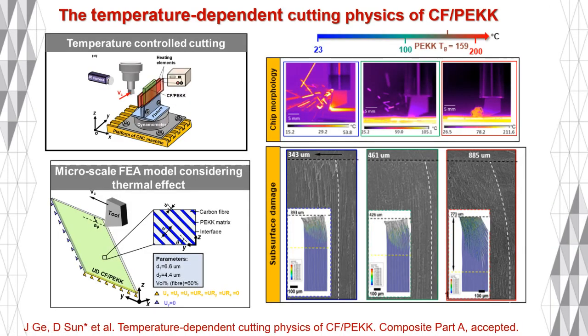In the final work package, my PhD student also developed the first microscale FEA model that considers the temperature sensitivity of the thermoplastic matrix. And this model, supported by experimental validations, has allowed us to develop a mechanistic insight into the microscale material deformation and fracture mechanics, both on the machined surface and below the machined surface under different temperatures.